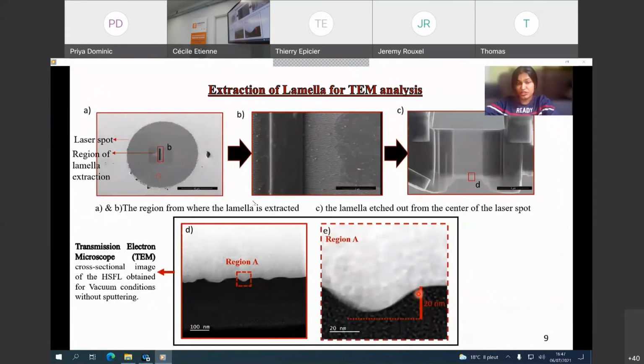transmission electron microscopy. So, extraction of lamella for TEM analysis. In figure A, you have a laser spot, and we extracted the lamella from the center of the laser spot where there are structures. And figure C is the image of the lamella extracted. The lamella is a very thin section of the material of less than 100 nanometers thickness, and in region D you can see the HSFL cross-sectional profile image obtained by TEM.